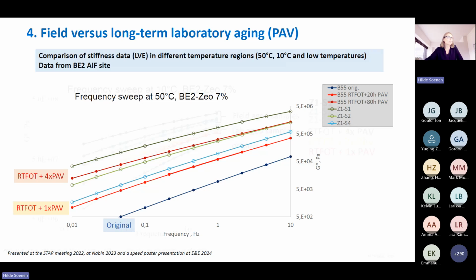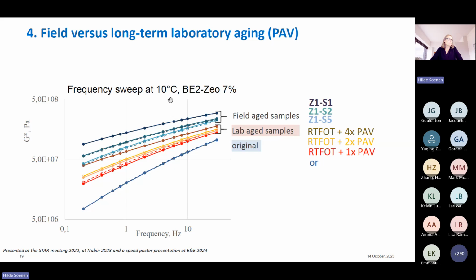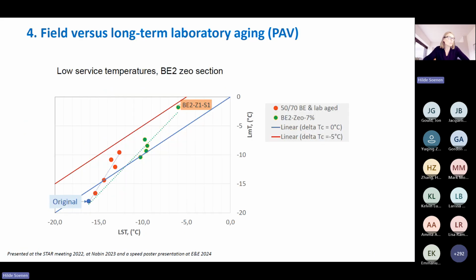But if we then go to lower temperatures, for example, here, frequency sweeps at 10 degrees, the same sample, the same binders, you now see that the lab-aged samples are all below the field-aged samples. So lab aging is, in this case, not sufficient to simulate the stiffness that you see in the field. And if you go to very low temperatures in the range of the bending beam, in this case this was measured with the 4 millimeter DSR, but all the samples were measured in the same way. And you see the lab aging is in this region and the field aging is here. So there is an even larger difference now in the stiffness levels that you observe at very low temperatures compared to lab aging. If you would have to age this one to the same stiffness as the top slice, you would need many lab PAV aging cycles.